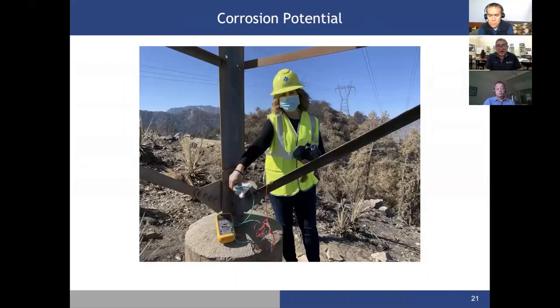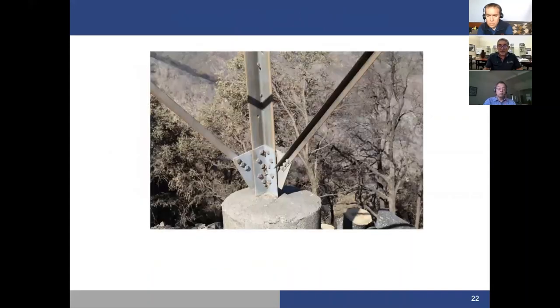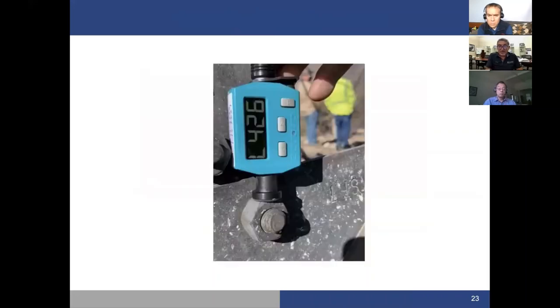Here, a technician is measuring the corrosion potential of different surfaces and identifying if the zinc is left on the surface or is gone, and there should be some protection after wildfire exposure. This area shows a non-affected leg of this tower. And then you can use hardness as a performance parameter that can determine the mechanical yield strength based on non-destructive testing. This is a very interesting way of determining without cutting the sections of the tower what's cooking there.